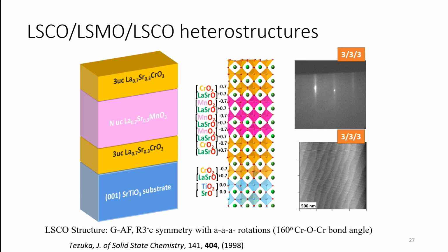So the experiment we wanted to do was hopefully relatively simple. We said that if you have an LSMO surface and you have something neutral or vacuum on top of it, you're going to have this charged surface. If there's a negatively charged MnO2 plane here and there's nothing on top, then you're going to have a net negative charge there. But what happens now if you take another material which has the same plus minus 0.7 charge stacking and put it on the top and bottom interface of these very thin films?